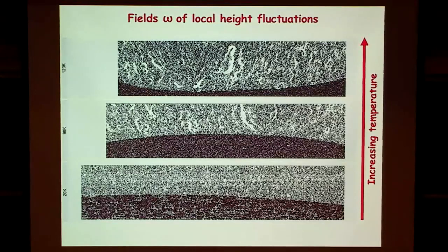This small scale regime is precisely associated with this process of micro crack ahead of the main crack. But what we see is some filtered information. We miss the overhangs. We have only one point at each location on the fracture surface. We miss the information on the overhangs, and the multi-affinity we see is reminiscent of this overhang structure due to percolation of microcracks or damage with the main crack. To explore this idea, we need to probably do simulation where we have information on the whole overhang structure and not only here.